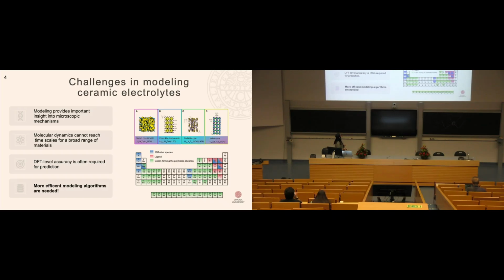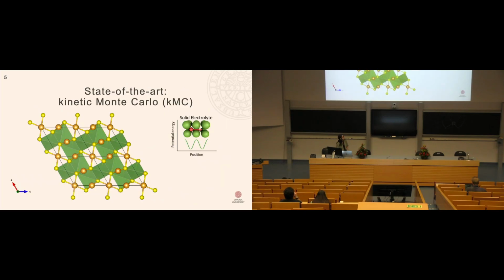So to be able to reach a broader range of materials, we need more efficient algorithms. Lattice-based kinetic Monte Carlo methods are used quite extensively for studying diffusion processes in crystalline materials where molecular dynamics isn't sufficient. And the hopping type motion, which is characteristic for the crystalline diffusion within this spatially rigid framework, makes a lattice model ideal.